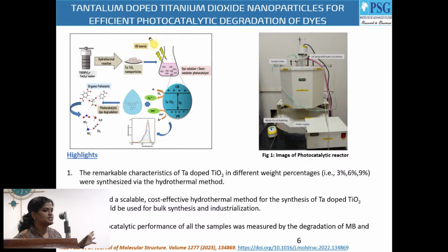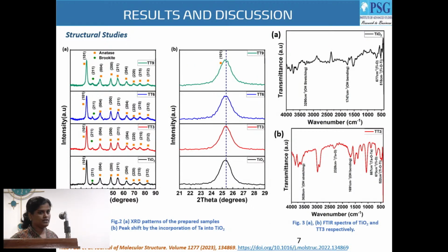We have synthesized tantalum-doped TiO2 in different constant weight percentages like 3, 6, 9, and we used the hydrothermal method, a cost-effective method. And these are the structural studies. XRD shows tantalum-doped TiO2 with different weight percentages and also pure TiO2. In TiO2 it shows a pure anatase phase with a small peak of brookite phase at the 211 lattice plane. We couldn't see any tantalum peaks there.